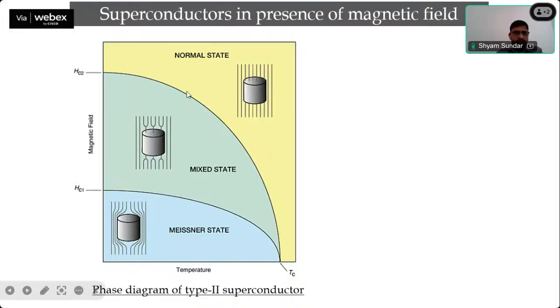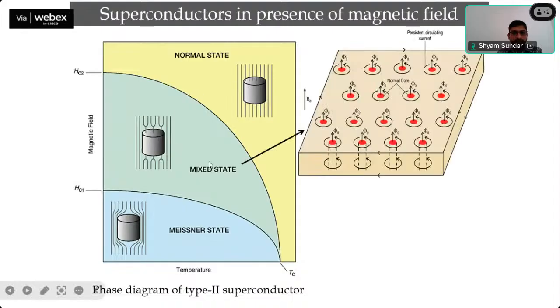And if you further increase the field above HC2, the magnetic field starts penetrating normally, which is basically the simple paramagnetic state. So we are most interested in the mixed state. So what exactly is this mixed state? Basically, in the mixed state you get these vortices. They carry superfluid current, and because of this current, you get a magnetic field at the core of these vortices.